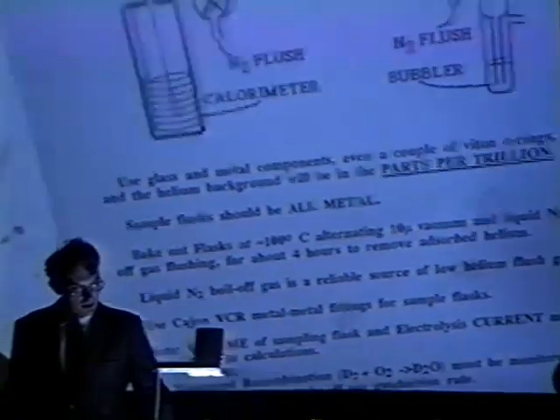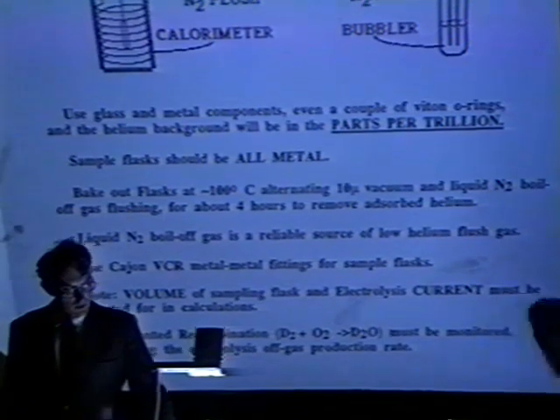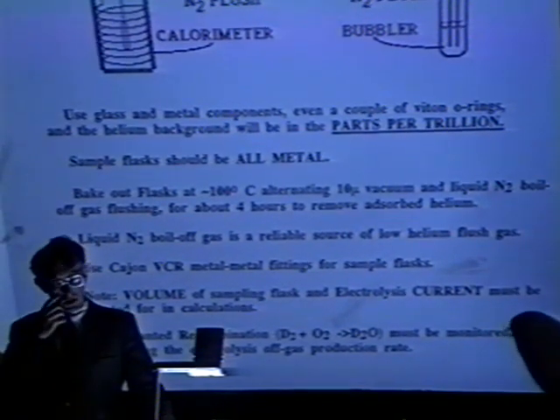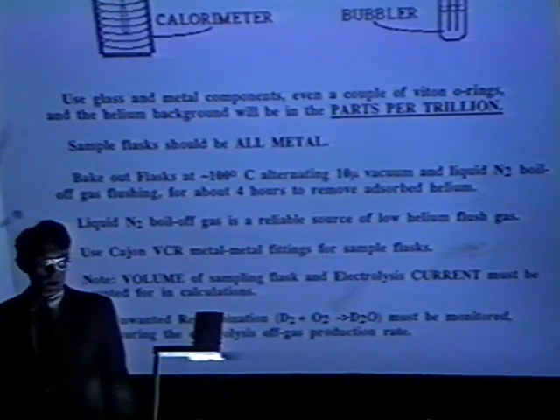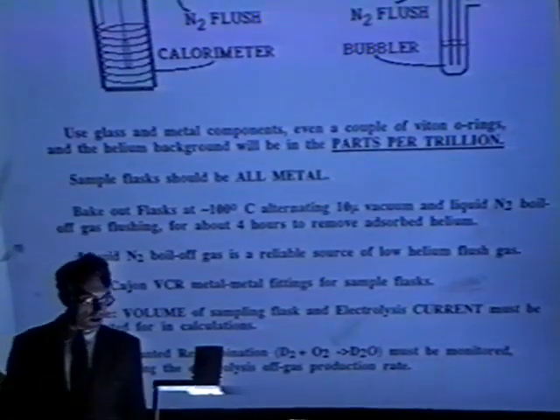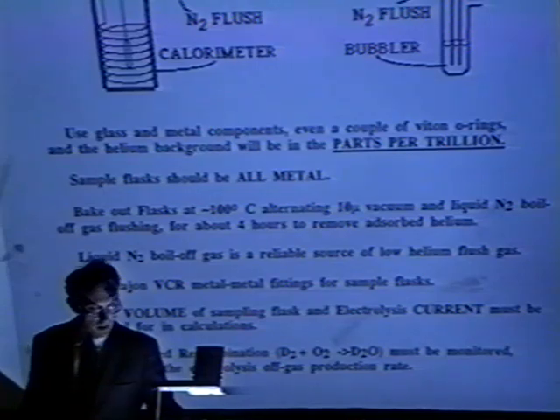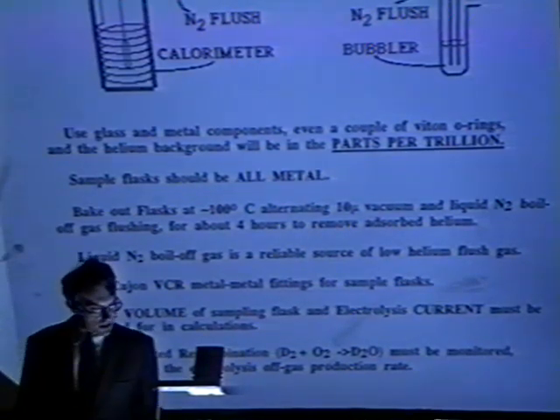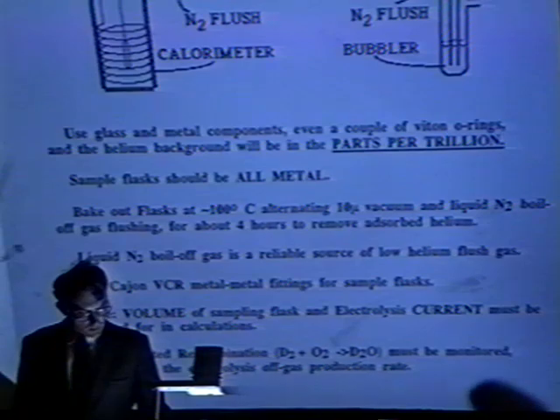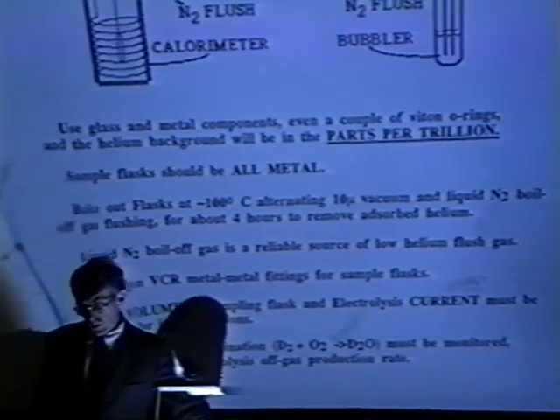You want to use, again, Cajon VCRs, metal fittings, wherever you can. And you're going to have to take into account the volume of the sampling flask and the electrolysis current in your calculations of how much helium you have for how much heat you're developing, how much energy you're generating in the system. And you've got to watch out in your calorimetry for unwanted recombination, because it, of course, creates an apparent calorimetric error unless you measure the amount of recombination that's there. Usually it's not a problem. Usually you don't have any recombination.